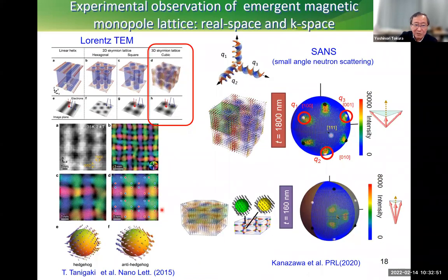So actually, we could confirm this monopole, anti-monopole structure, or more correctly, the hedgehog, anti-hedgehog crystal, again with the Lorentz transmission electron microscope. But in this case, we only observe the 2D projection, so we need some comparison with simulations. This is a simulated monopole, anti-monopole, hedgehog, anti-hedgehog crystal, two-dimensional projection like this one. And this is the simulation. Maybe you can see an almost perfect coincidence with the experiment. Also the temperature and magnetic field dependence also confirmed this.